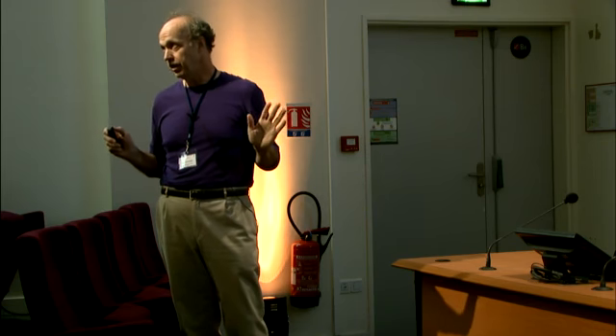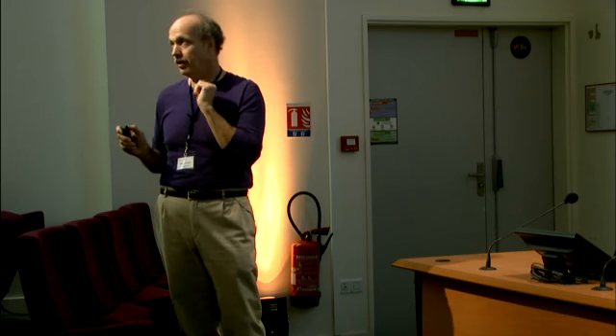This is a plot down here of the specific activity where we've taken into account the total number of surface platinum atoms in these particles and then plotted it as a function of the size of the particles. And you can see these are really not very active materials until they start getting bigger, and they never are as good as bulk platinum. That's fine. We're not trying to make a better catalyst here or use platinum more effectively or anything like that. We're just trying to make really monodispersed materials with a very small number of atoms that we can compare to theory.